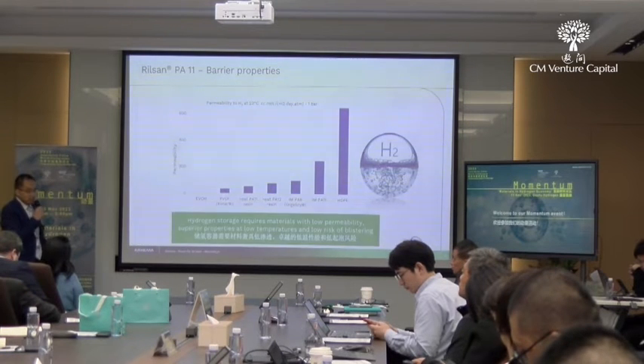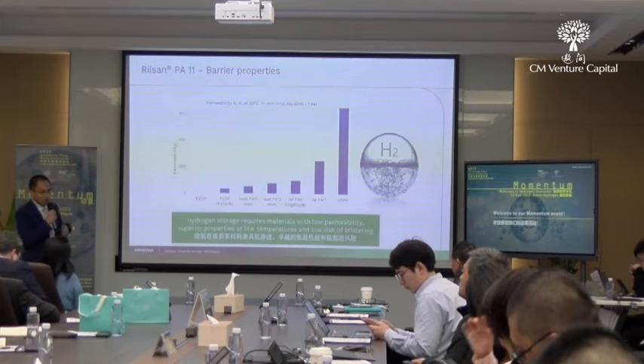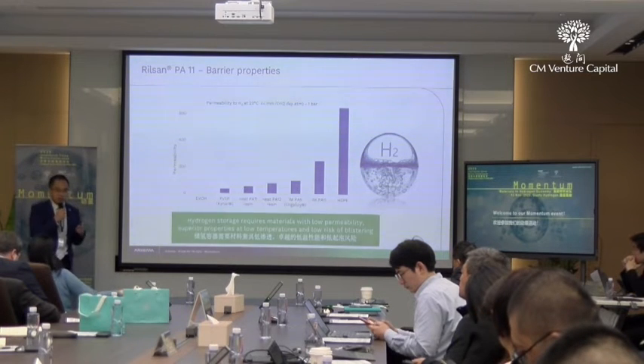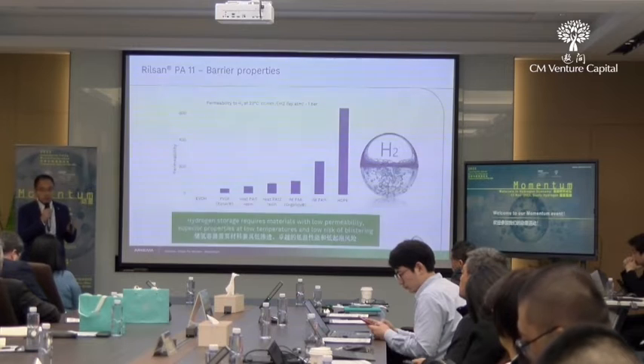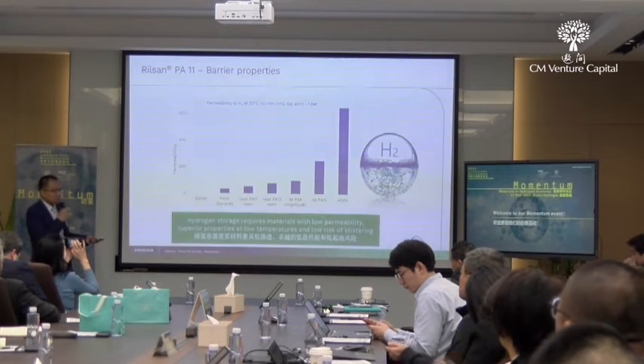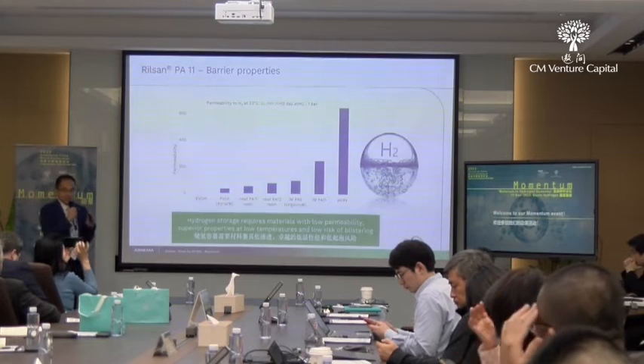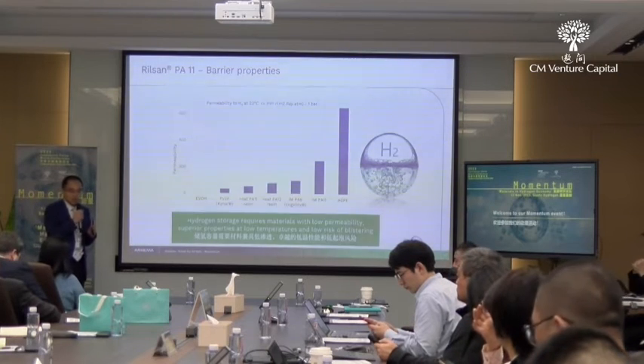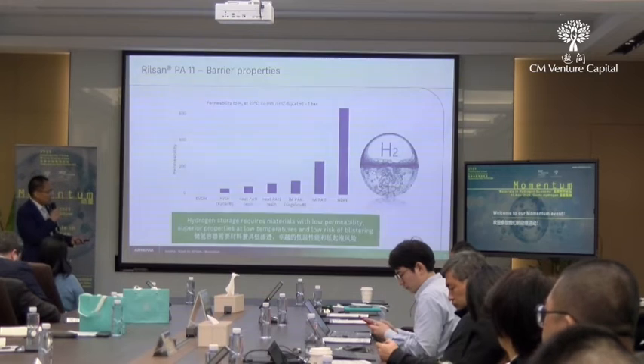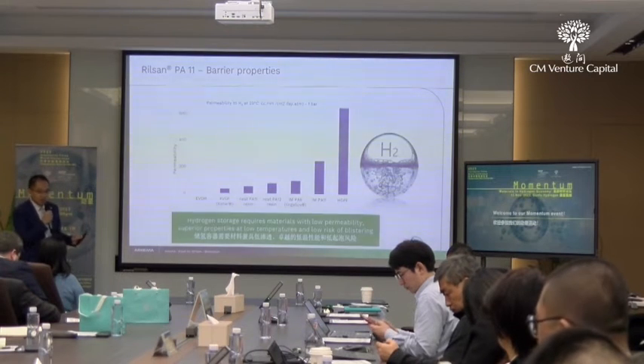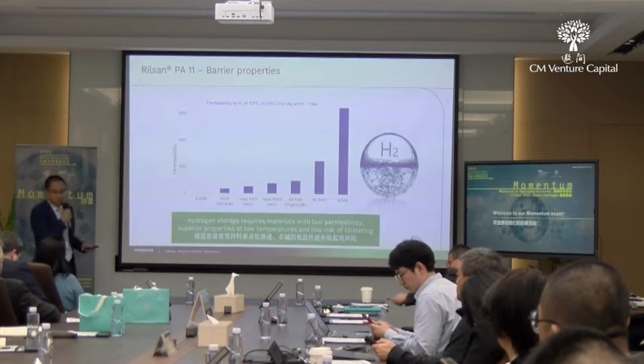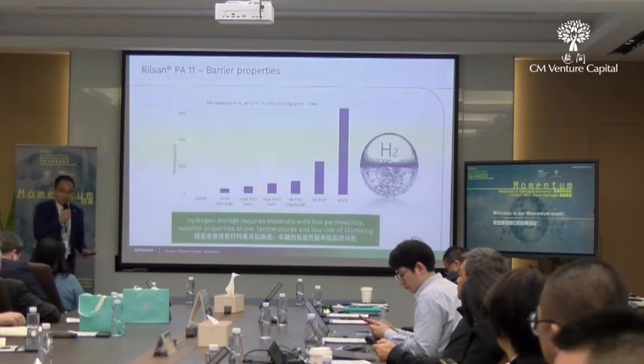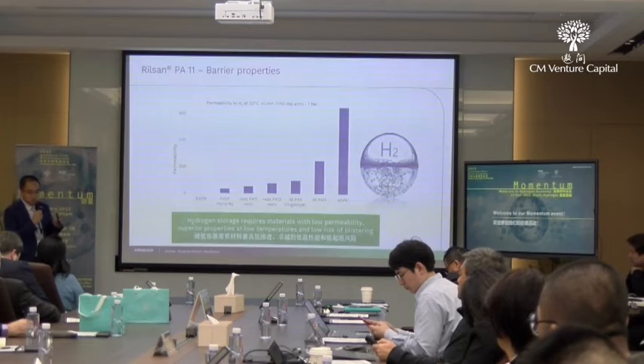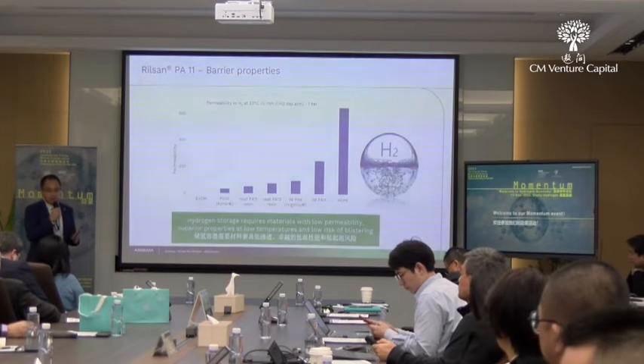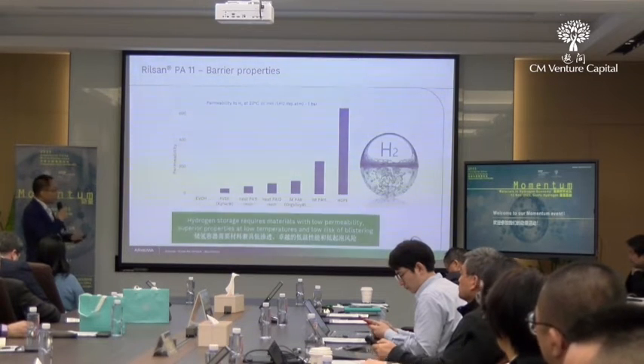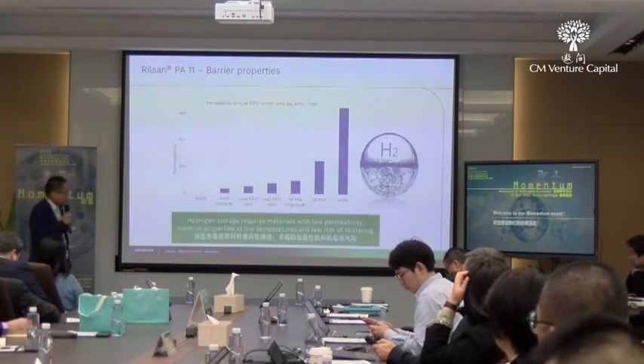And another one is HDPE. You may see some articles or information from Europe. It has been used for many years for CNG tanks, the Type 4 CNG tanks. But you may see very little for hydrogen, because the permeation for HDPE is quite a bit higher than polyamide. So why polyamide is becoming more and more popular for Type 4 tanks is mainly due to the permeation.